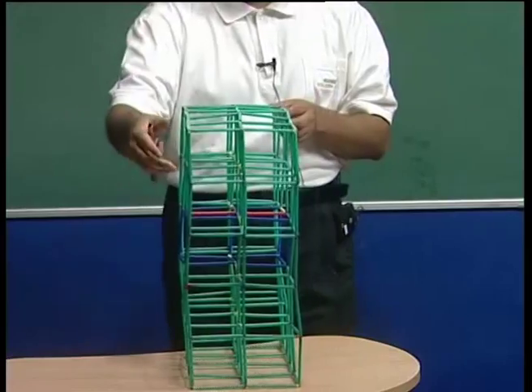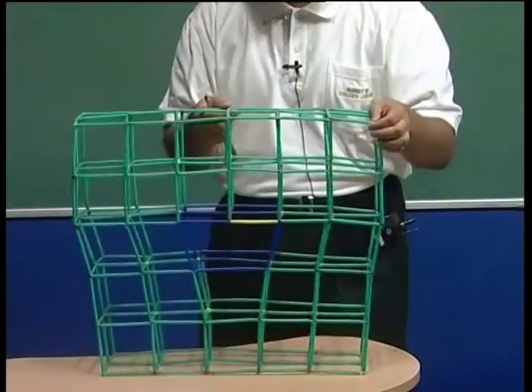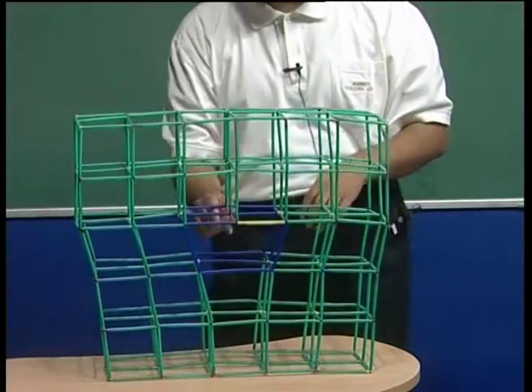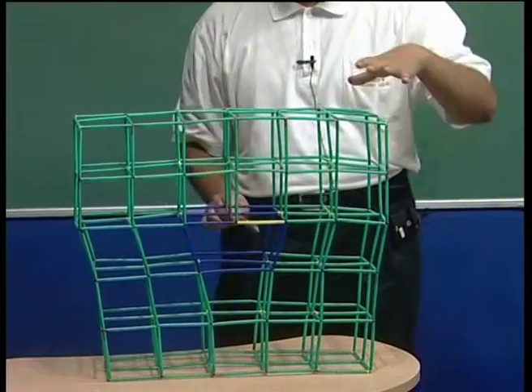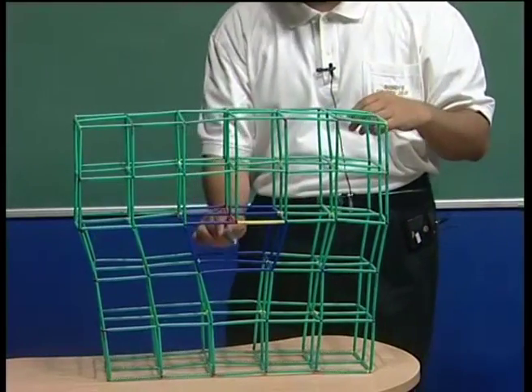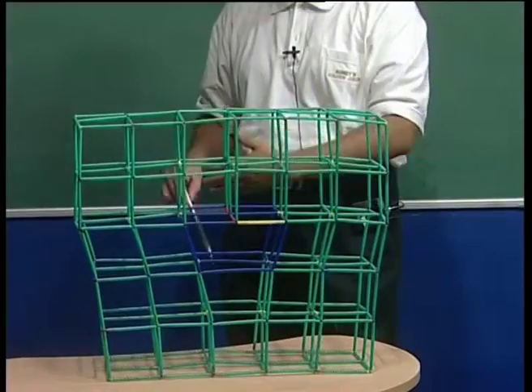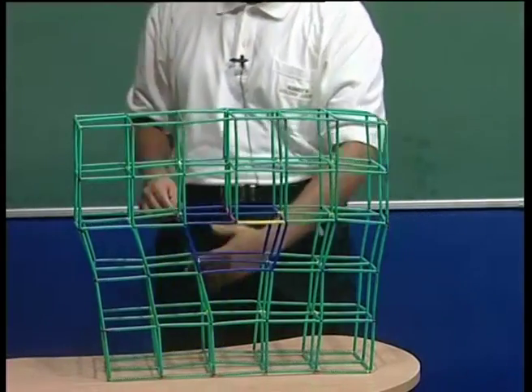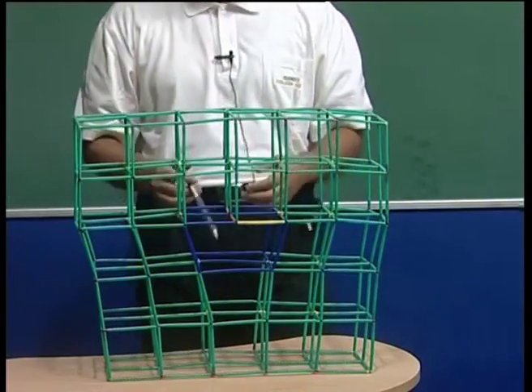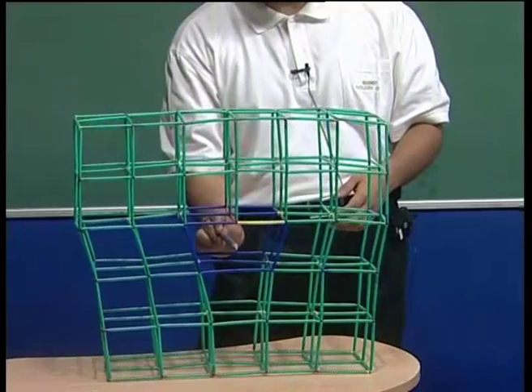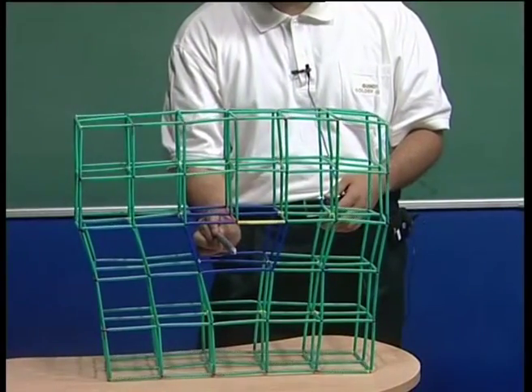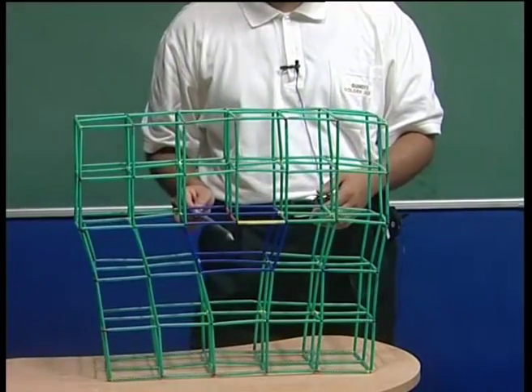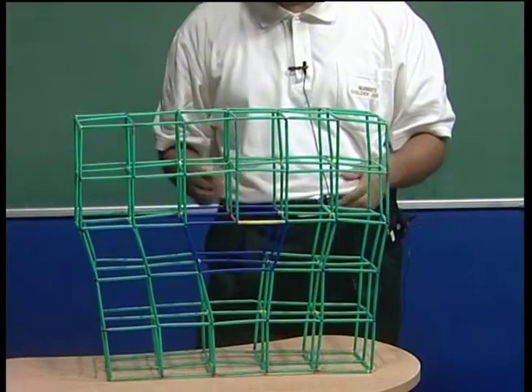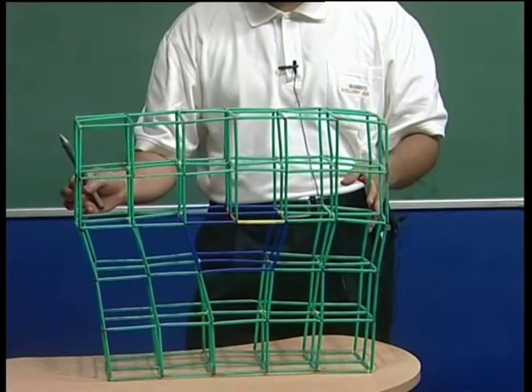So looking from this direction, I cannot see the dislocation. So the dislocation is best viewed from this direction, and in this case the dislocation line is starting from the front face of the crystal, and of course I have only taken 2 unit cells here. Typically a straight dislocation line would run and end at the back side of the crystal. So the first terminal point of the dislocation on the free surface would be the front free surface, the other would be the back free surface. And therefore this is my edge dislocation in a single crystal.